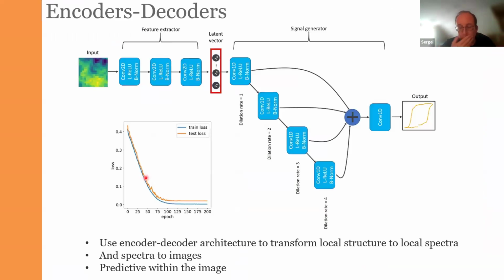So now let me briefly show a few more examples of how we can use the VAEs. And here the key thing is that nobody told us that it has to be an autoencoder. So in principle, we have multiple experimental scenarios where we can measure pairs of variables. For example, we measure local structure and we measure the local spectrum. So it can be piezoresponse microscopy where the image is domains and the spectra are hysteresis loops. It can be STEM EELS where we measure the local structure in STEM and take the local spectroscopy in EELS. It can be nanoindentation where we measure the local structure visible in the SEM optics and we measure the local indentation curve. The same type of approach obviously applies to molecular structures, where we can input the molecular structure and the output can be adsorption spectra. So there are multiple examples where we have pairs of disparate information.